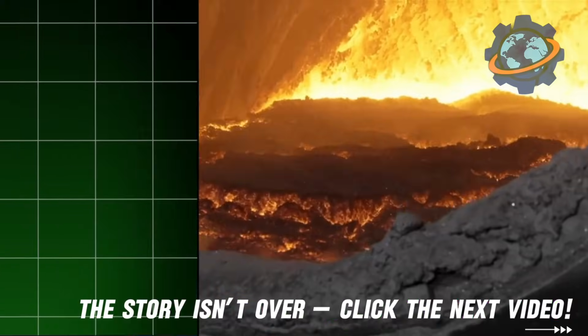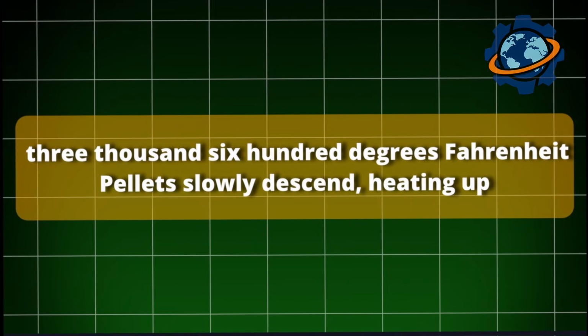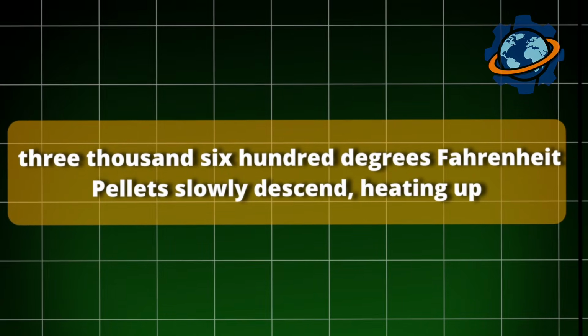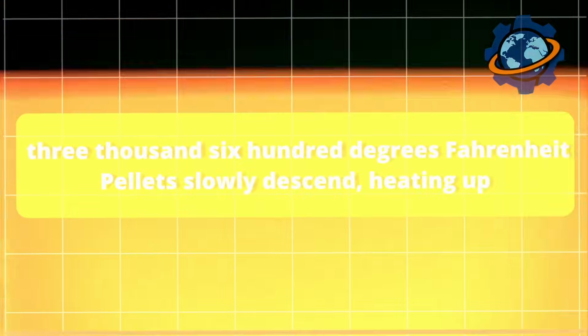From below, through tuyères, openings in the walls, hot air is blown in. Air temperature, 2,200 degrees Fahrenheit. Pressure, 4 atmospheres. Coke ignites. Temperature in the furnace's lower section reaches 3,600 degrees Fahrenheit. Pellets slowly descend, heating up. Different reactions occur at different heights.